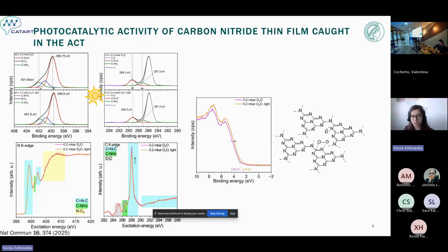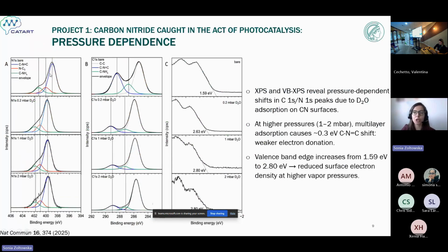What we are missing here is the kinetically faster hole transfer, presumably from the carbon side to the bound oxygen of the heavy water. However, here we were working with quite particular conditions, 0.2 millibar of water. We wanted to know, is there any pressure dependence? Will we be able to observe the same changes if we increase the water pressure?